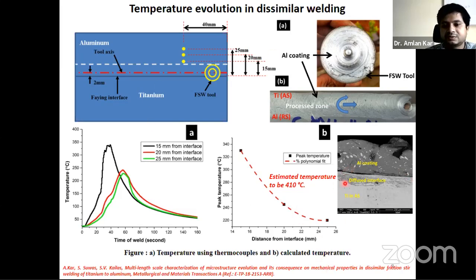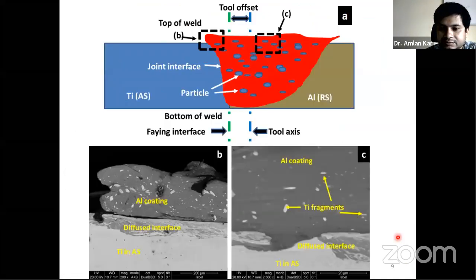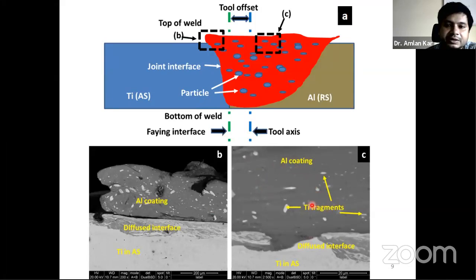And that's why whatever deformation has taken place in titanium is a low temperature deformation. Now I'm coming to what kind of deformation has taken place over here. You can see here the coating developed cross-sectionally, and we have also seen many small particles, which from the backscatter image could be titanium particles. But we have also observed that this is not fully a titanium particle. This is an intermetallic particle.